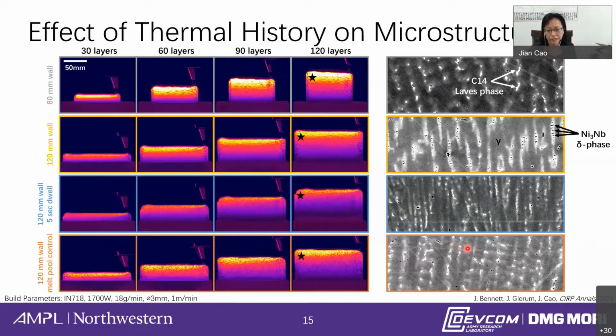The next thing you observe is the difference in the amount of Laves phases, which are nucleated during solidification. We know that the Laves phase is detrimental to tensile strength. So you can also observe the difference in how the delta phases come out from different thermal histories. These delta phases correspond to the second band that I mentioned earlier, because they cut through the Laves phases and actually strengthen the material. Which is why the second zone also very much affects the mechanical property, right?